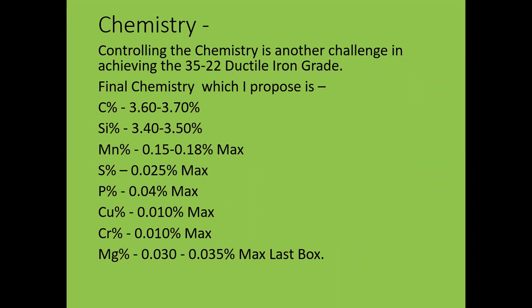Chemistry. Controlling the chemistry is another challenge in achieving 35 by 22 ductile iron grade. Final chemistry which I propose is carbon 3.6 to 3.7, silicon 3.4 to 3.5, manganese 0.15 to 0.18, sulfur 0.025 max, phosphorus 0.04 max, copper 0.01 max, chromium 0.01 max, magnesium 0.03 to 0.035 max for the last box. Here carbon, silicon and manganese play an important role, whereas copper and chromium in traces need to be controlled.